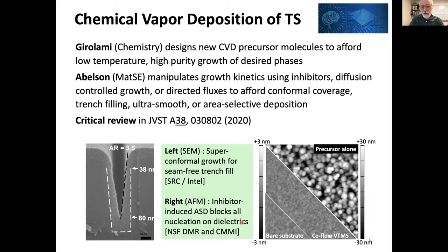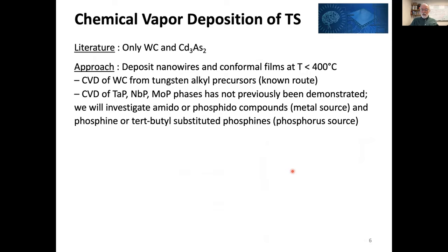On the right, a snapshot. This is work under NSF, both from DMR and CMMI, where we've introduced a reversible inhibitor that creates area selective deposition. This is an SiO2 substrate. Here is an atomic force microscope image where you see nothing on the bare substrate. You see film nucleation in the absence of the inhibitor, and in the presence of the inhibitor, it's just the bare substrate. Now, I mention this because we are very conscious of wanting to develop topological semi-metals, but to incorporate them in a realistic way in microelectronics fabrication. So these are interconnects, right? So we're going to have to fill trench and via structures. If we can get other effects like area selectivity, that's fantastic.